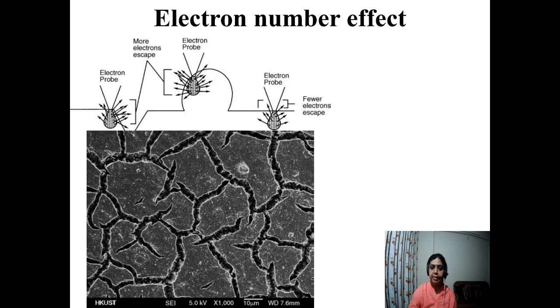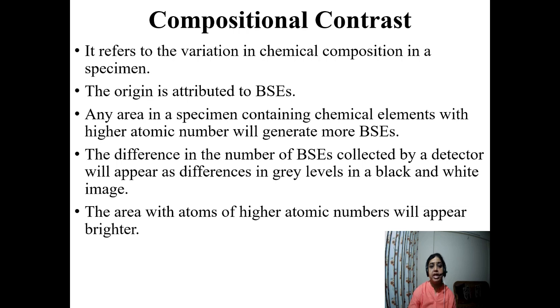Let's take an example. This is an example of the electron number effect. So this is your grain boundary. Can you see this bright line? Here the electrons are escaping from this point, so that's why they are brighter. However, this is a flat surface, so fewer electrons reach the detector. So we can see the grain boundary very nicely. This is a flat surface, fewer electrons reaching the detector, so it is moderate. However, grain boundaries are quite bright in nature. Here we can see some inclusion, again something. That's why it can be used for 3D analysis also, due to the electron number effect. Let's come to the compositional effect.